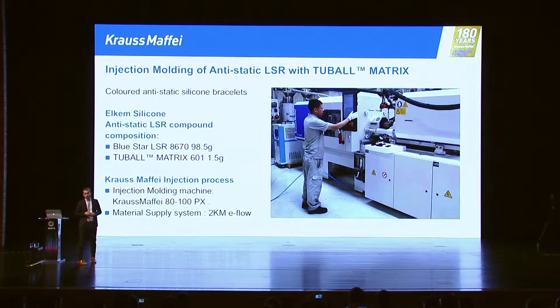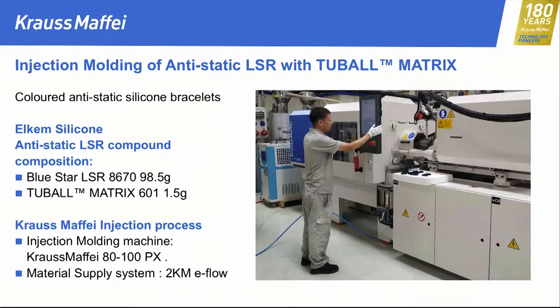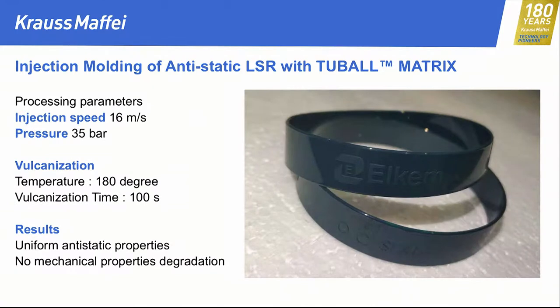And this is the machine you will be able to see in the industrial zone. That's our PX, the electric machine with 80 tons of clamping force and an injection unit of 100. And here you can see it. We have 98.5% of just standard LSR material we want to process and only 1.5%, of the Tuball matrix material. You may ask, by the way, this is the Elkem material from Blue Star, which is also, let's say, a sister or a brother in our company, below ChemChina. And this is the result, what you can see also in the industrial zone later.